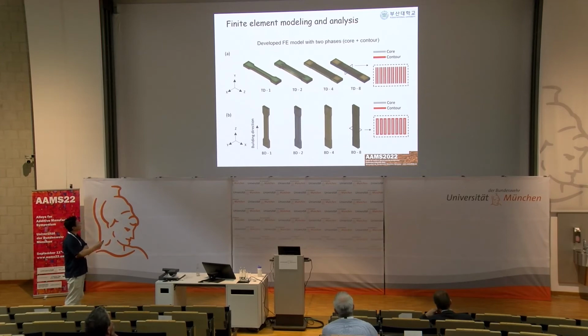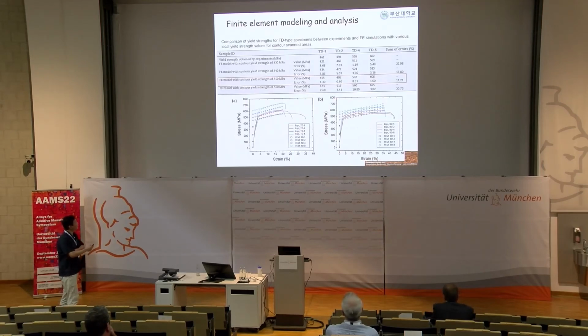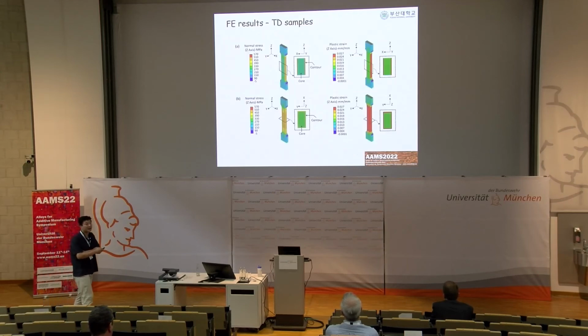We considered the contour scanned area as a slightly different material for later use in design, along with different directions. So here in the cross section, we can see that the red is the surface area where the laser is scanned twice by the contour, and gray is the core. By fitting with the experimental results, we could really reproduce the size effect with this very simple finite element model, so that can be used by mechanical engineers.